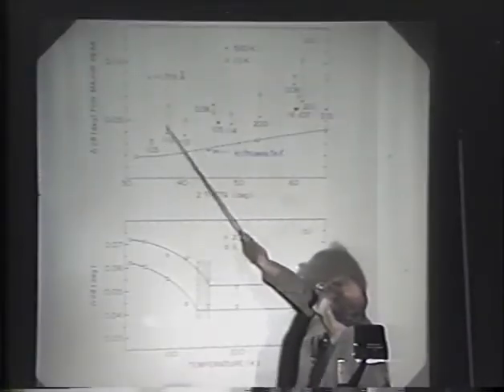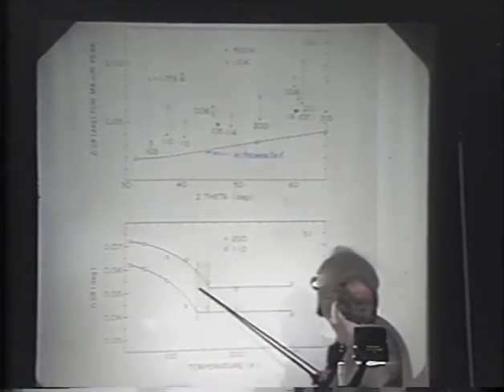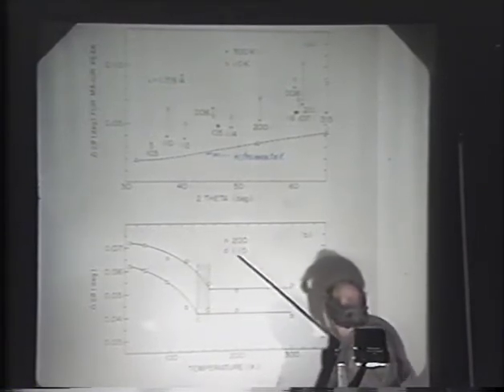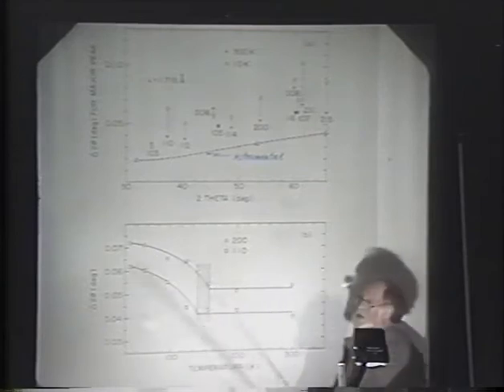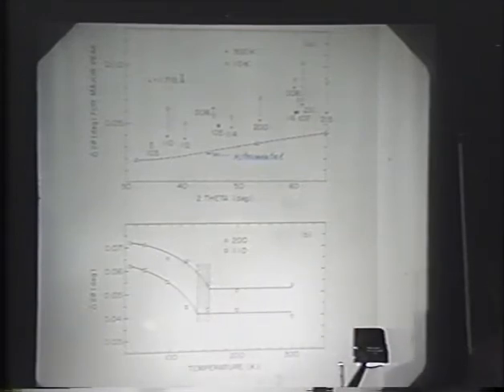Let me just show the broadening then, because it's important. Here is the broadening, and here's instrumental resolution, and all the peaks on cooling broaden, and both the 200 and 110 peaks broaden on cooling. And because both 200 and 110 broaden on cooling, we cannot have an orthorhombic transition. It must be a transition to a monoclinic phase. And the amount of distortion is quite small.